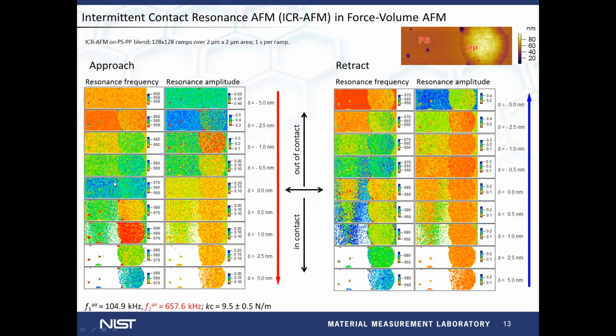Here is an example of such measurements on a polystyrene-polypropylene blend. Polypropylene is in the form of these round areas, in a semi-crystalline phase. The scan was 128 by 128 pixels over a 2 micron by 2 micron area, and was very slow, 1 second per ramp. And here are shown maps of resonance frequency and resonance amplitude along approach and retract, at different indentation depths, going all the way from -5 nanometers out of contact to 5 nanometers into contact. Because the force volume was operated at a constant set point of 25 nanometers, and there is a stiffness difference between these two materials, beyond about 2 nanometers indentation depth the measurements were available only on polypropylene regions.